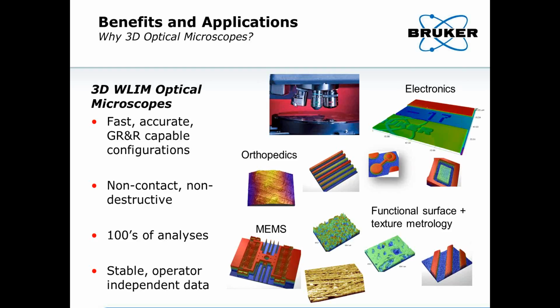You can see larger area, 5x or 2.5x or even 1x fields of view, which can be 10 millimeters or more on a side, up to a 50 or 100x objective, which might get you an image down to as small as 25 by 25 micron square. All of those fields of view can be measured quickly with accuracy, repeatably and reproducibly. And so that's what I mean by fast, accurate GR&R capable configurations.